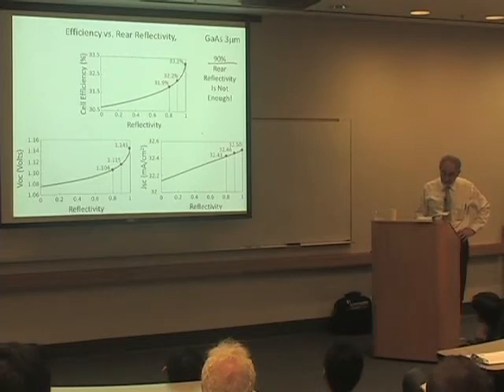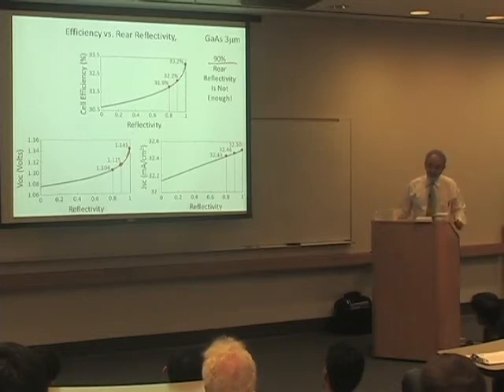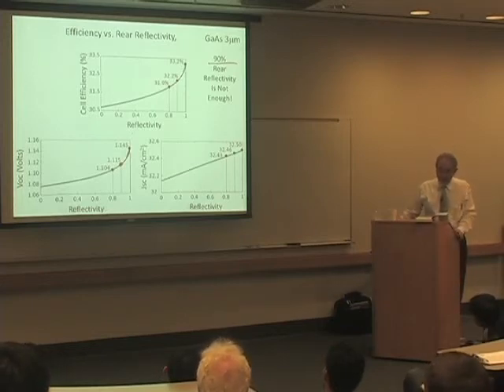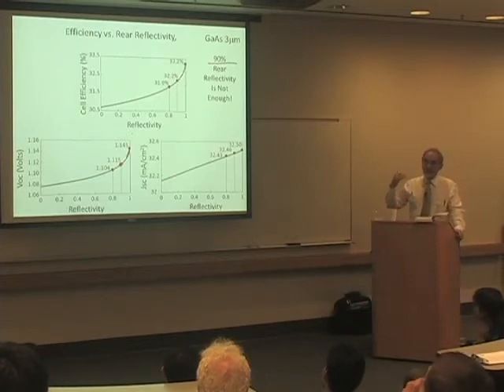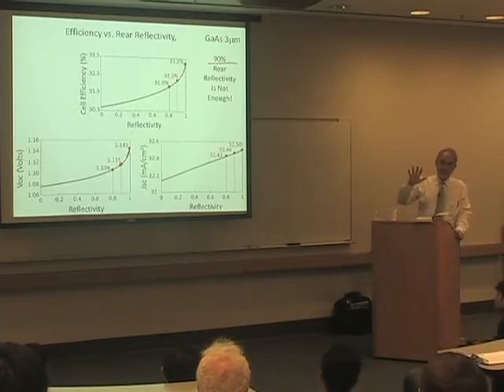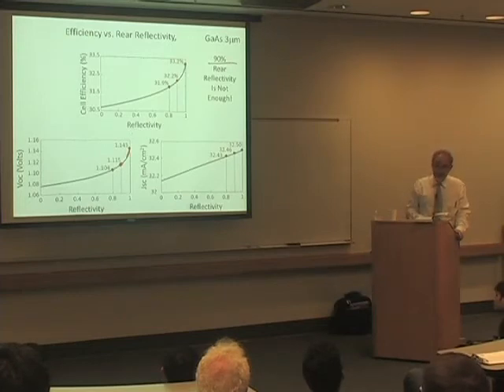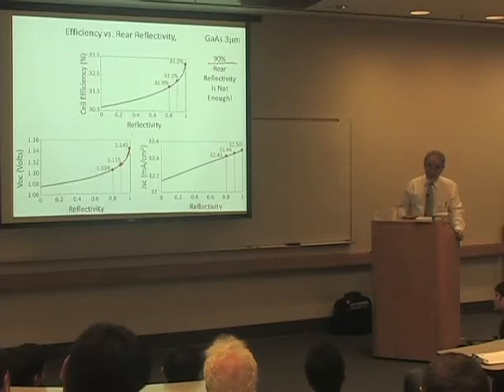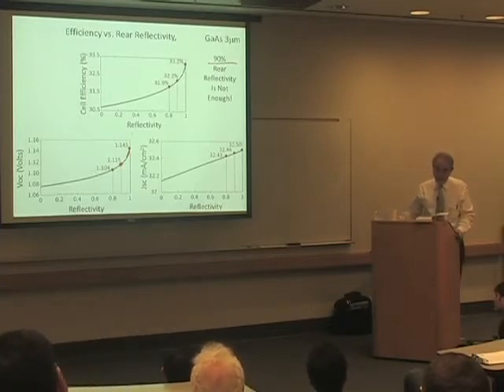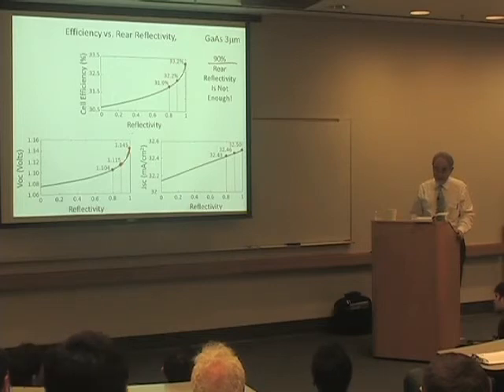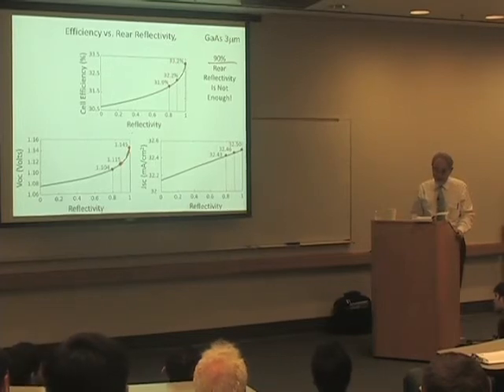I mean, it's good, but look at what happens to the voltage. At 90%, you have a good voltage. But as you go above 90, 95, 98, 99, you get a tremendous steepening and tremendous increase in the open circuit voltage. And so the lesson of this is that if you're talking about a really good solar cell, don't worry about the transport of the electrons and holes. That's already taken care of. The real issue in a really high efficiency solar cell: manage the photons. Help them get out, and have a good reflector, have good internal luminescence yield, etc. But good means 90% is not enough. It should approach 99 if possible.